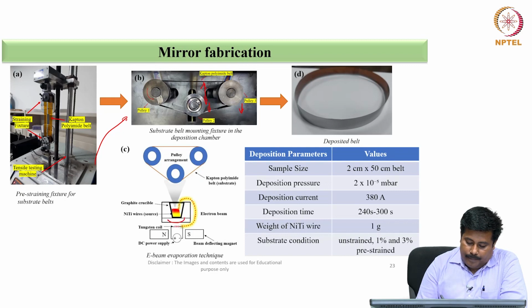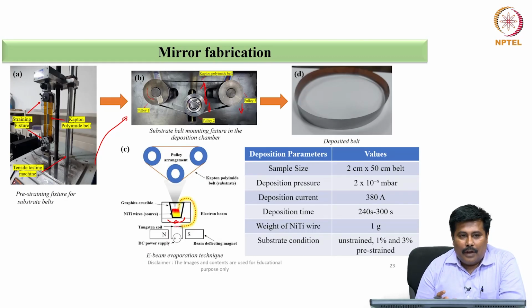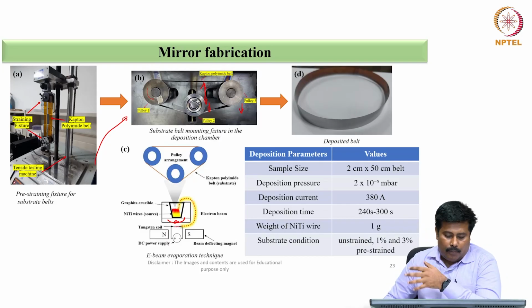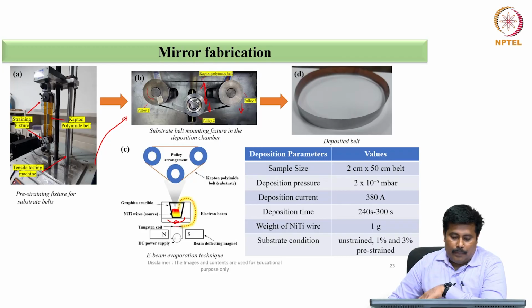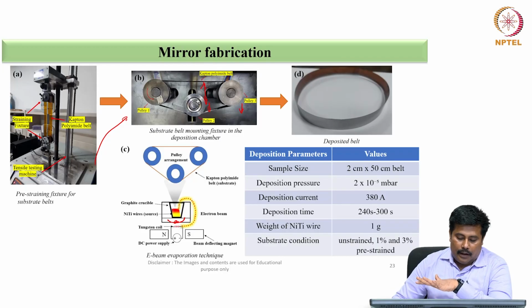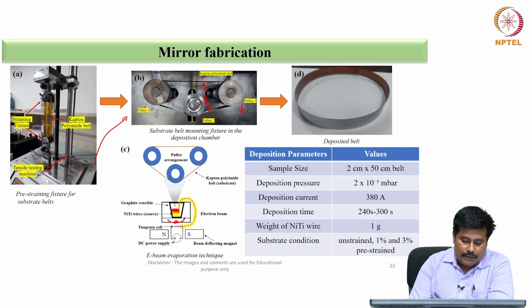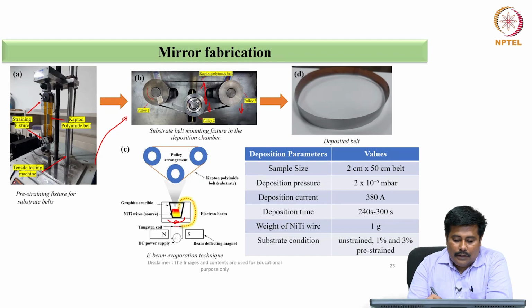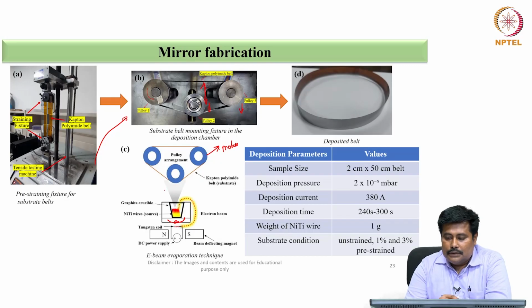Now we have a boat kind of arrangement. In this arrangement, we have already kept the pellet which has been manufactured, of the requirement to make an appropriate composition. Now an electrical biasing is applied on it. These electrical biasings are capable enough that evaporation persists, and the deposition is a continuous deposition. Since you have a pulley arrangement, these pulleys are connected with the motor and the idler pulley, and when the rotation happens, there is a continuous deposition of the material. This continuous deposition results in a deposition belt over here. The overall deposition is in the form of a sample size close to around 2 cm to 50 cm belt. The deposition pressure is in the range of 2 into 10 power minus 5 millibar.